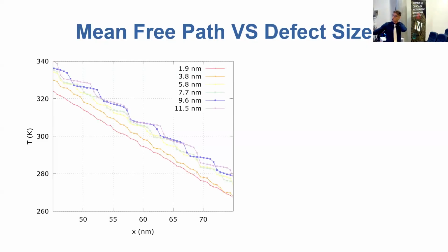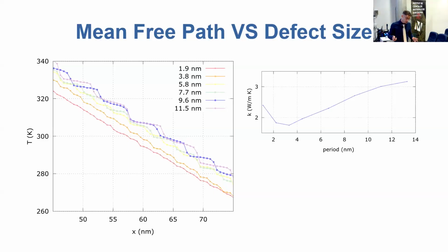If we repeat the study, so we apply a definite temperature bias, we wait for the reaching of a steady state, and we compute the steady state temperature profile, which is shown here. You can see that when the mean free path of the phonon, so the distance the phonon travels, is much longer than the superlattice period, we can change the superlattice period, because we cannot really change the mean free path. When the superlattice period is much shorter than the mean free path of the phonon, the phonons basically experience a sort of continuous material with average properties. So the superlattice period does not appear in the temperature profile.